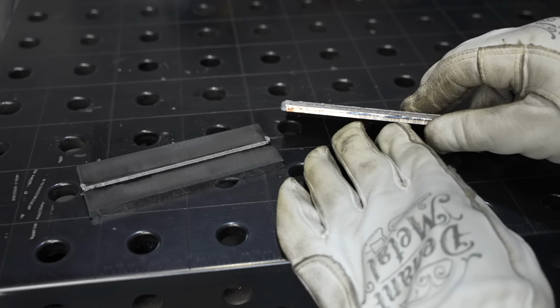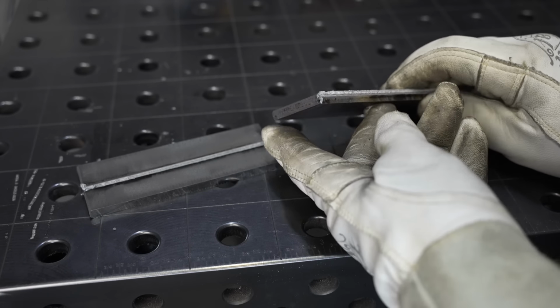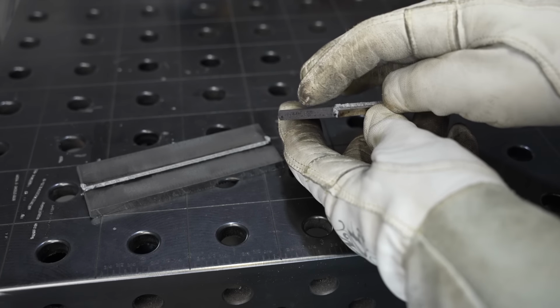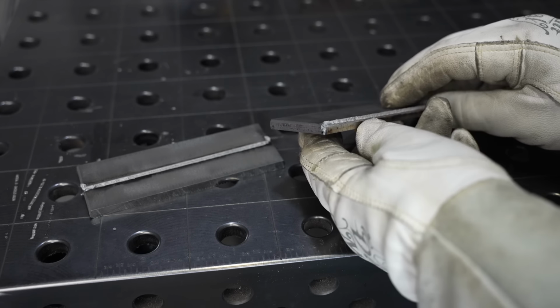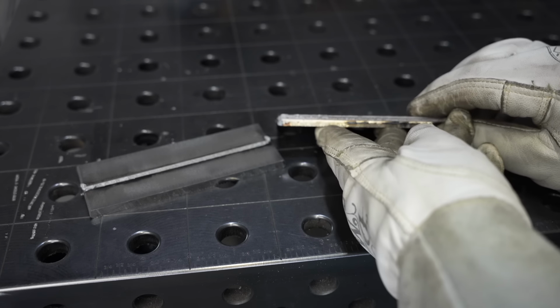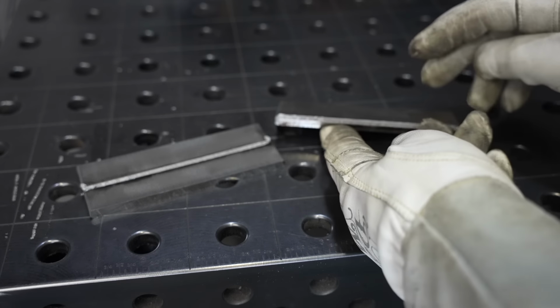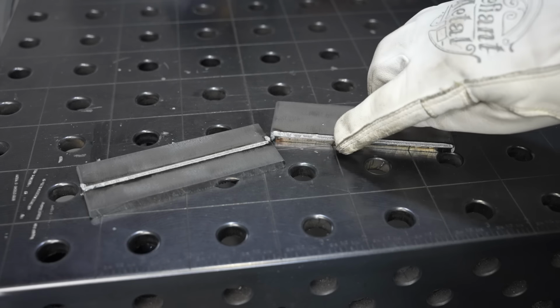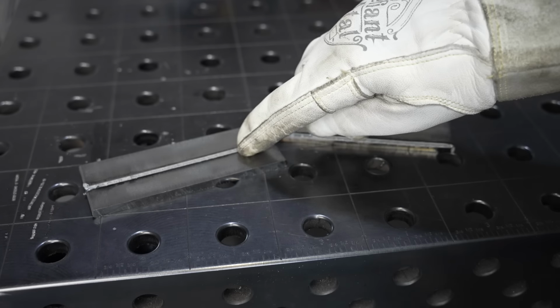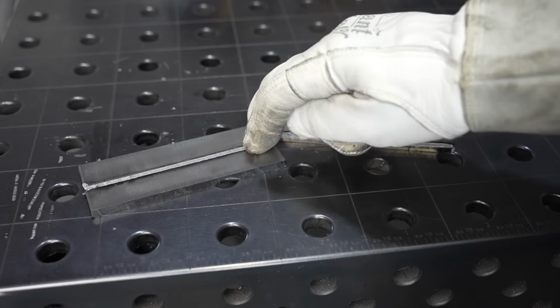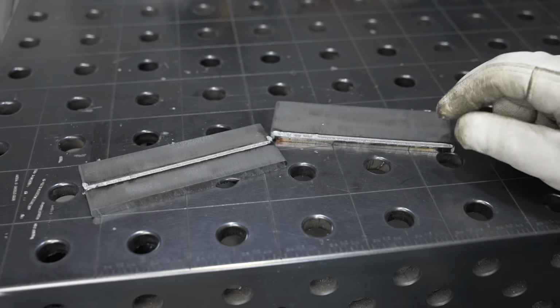Now, there is a straight line here, which usually would indicate that you didn't get into the root of the joint, except this is an automatic process. And if you look, that straight line is significantly below the surface of the plate. So we had good penetration into the root. The other thing that you're looking for is any porosity or discontinuities in here, and we don't have anything like that. So it's a good, sound structural weld that passes a fillet weld break test.